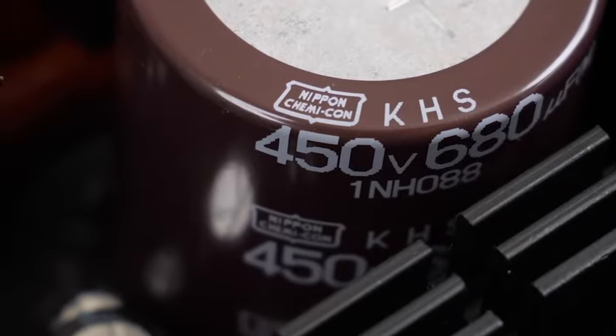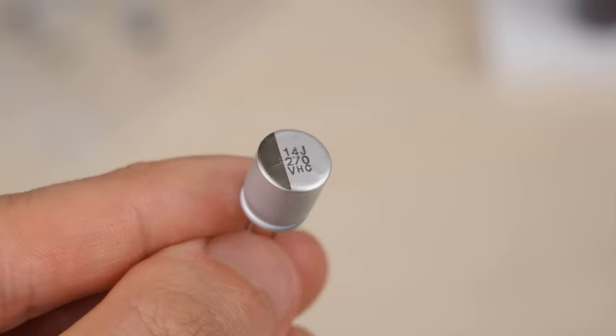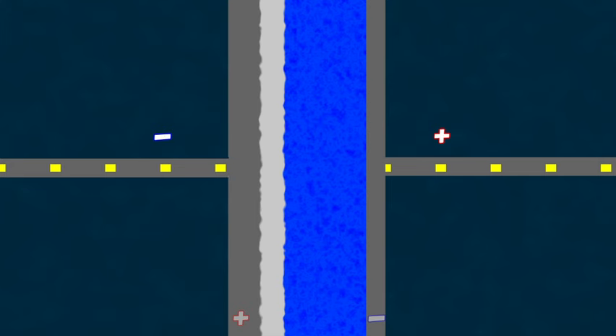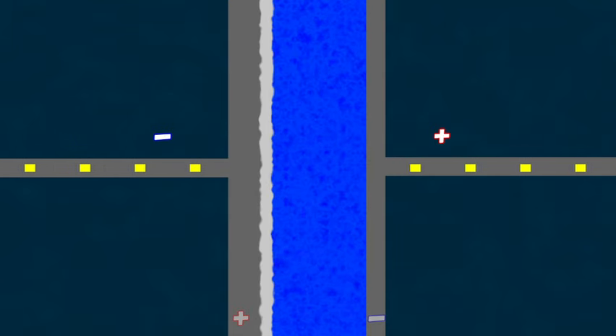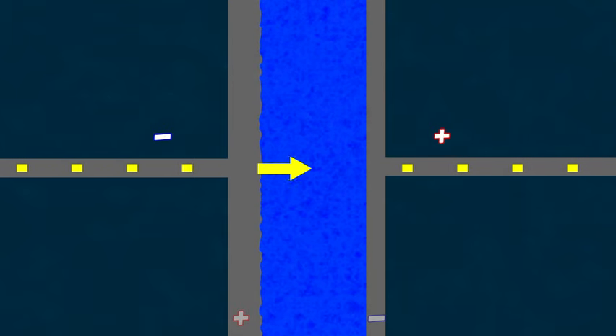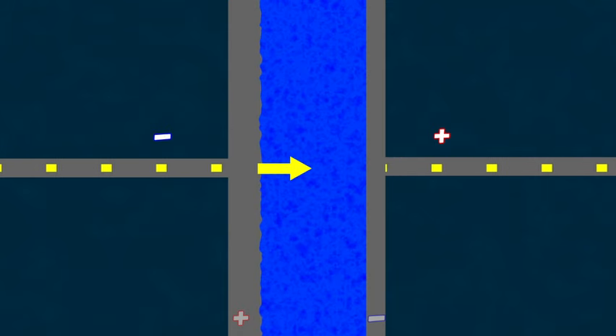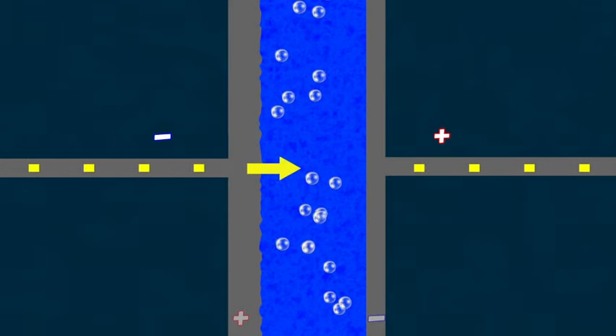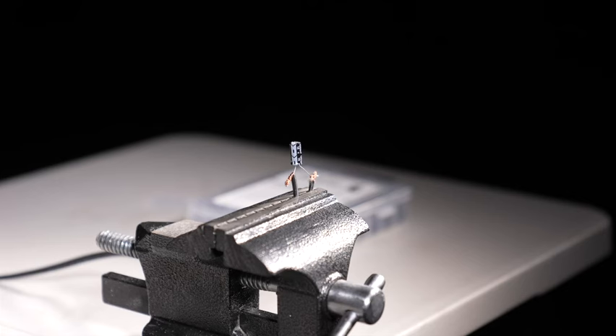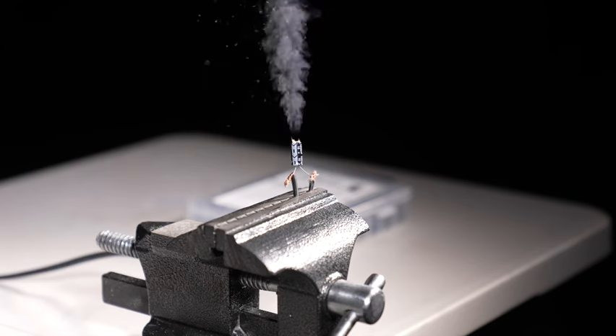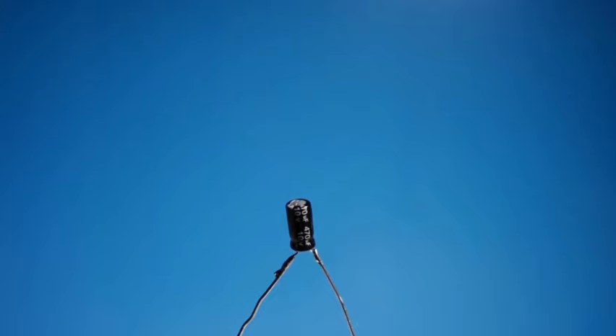However, electrolytic capacitors have several serious drawbacks. Among other things, they are polarized, which means they can only be connected to a circuit in a certain way — plus to plus, minus to minus, and never the other way around. The issue is that if such a capacitor is connected with reverse polarity, electrochemical processes in the electrolyte will lead to the dissolution of the oxide layer and direct contact between the aluminum of the anode and the electrolyte. This will cause the capacitor to break down, and current will flow directly between the cathode and the anode. When current flows, all substances heat up, and the electrolyte is no exception. If the voltage is high enough, the electrolyte can even boil. The vapor produced will accumulate inside the capacitor's case, increasing its pressure, and the capacitor might even explode. I strongly advise against experimenting with capacitors for the sake of amusement. An explosion can be quite powerful, and the flying debris from a ruptured capacitor can cause serious injury. Don't try this at home.